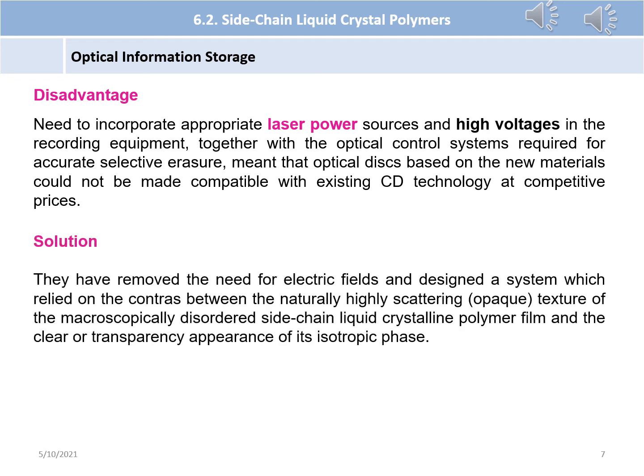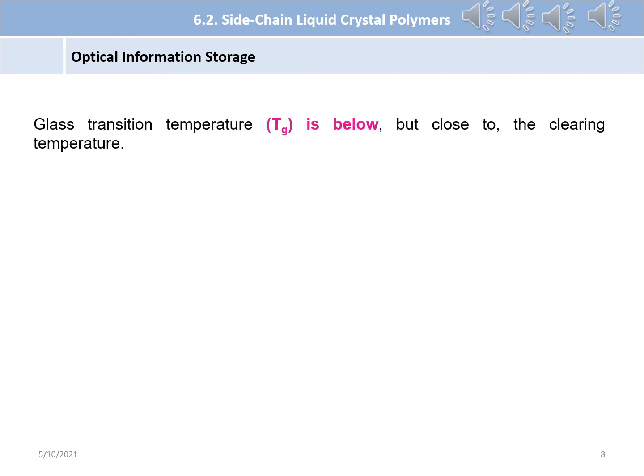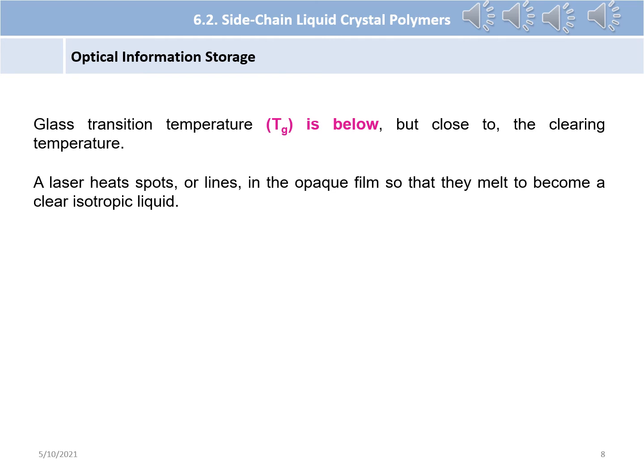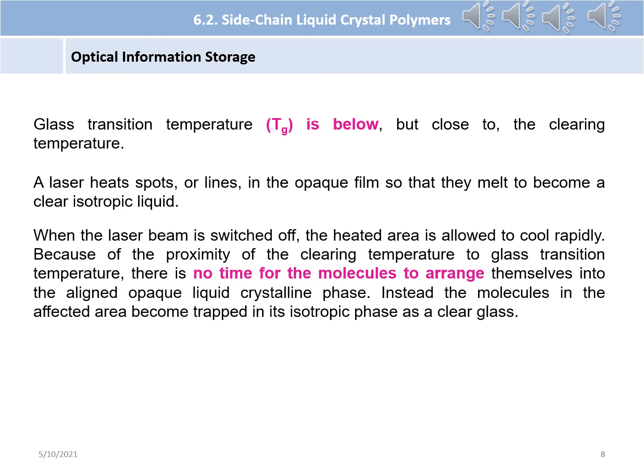As a solution, they removed the need for electric fields and designed a system which relied on the contrast between the naturally highly scattering, opaque texture of the macroscopically disordered side-chain liquid crystalline polymer film, and the clear or transparent appearance of its isotropic phase. The glass transition temperature, Tg, is below, but close to, the clearing temperature. A laser heats spots, or lines, in the opaque film so that they melt to become a clear isotropic liquid. When the laser beam is switched off, the heated area is allowed to cool rapidly. Because of the proximity of the clearing temperature to the glass transition temperature, there is no time for the molecules to arrange themselves into the aligned opaque liquid crystalline phase. Instead, the molecules in the affected area become trapped in the isotropic phase as a clear glass.